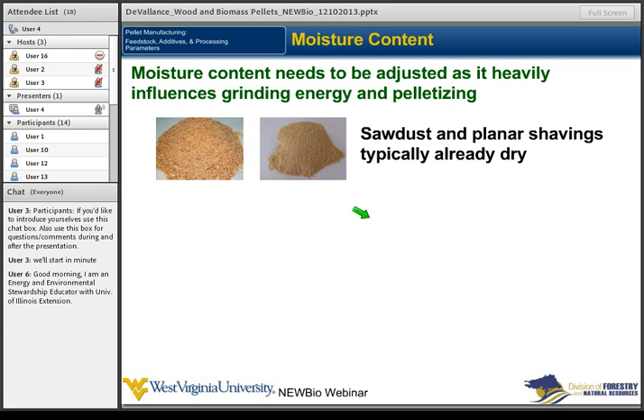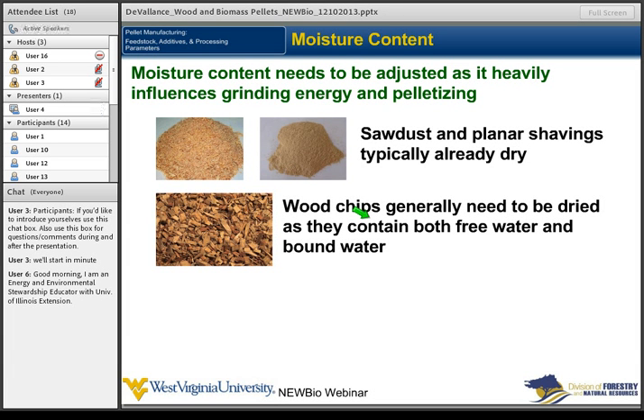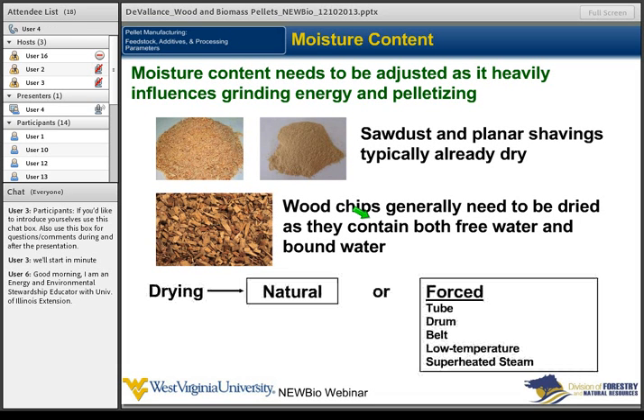So typically if we get sawdust and planer shavings in, it's going to hopefully be dry unless it's been sitting out for a long time. So we don't do too much in terms of drying those things down. Wood chips, on the other hand, generally need to be dried. They contain both free water and bound water. Bound water is the water in these wood chips below the fiber saturation point that's bound in the cells. It's harder to take out. Free water comes in and out pretty easily once the bound water fills up and these are saturated. So it takes a lot of energy to get this water out of these chips, especially once it gets down into the bound water range.